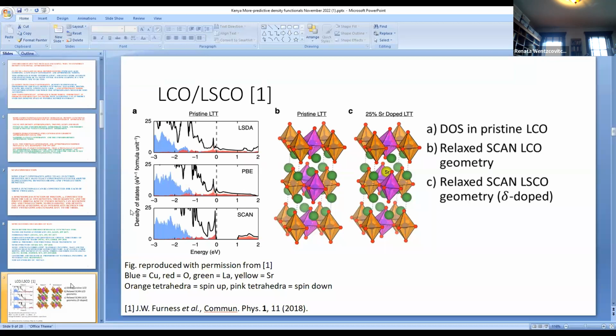What happens here is that, if you look at the pristine material on the left, you see the density of 1-electron states as a function of 1-electron energy. In LSDA and PBE, lanthanum copper oxide is a metal - there is no gap. But experimentally, there is a fundamental gap of about 1 electron volt. When we apply SCAN to this material, we get the gap, and in fact we get about the right gap. The gap opens up.